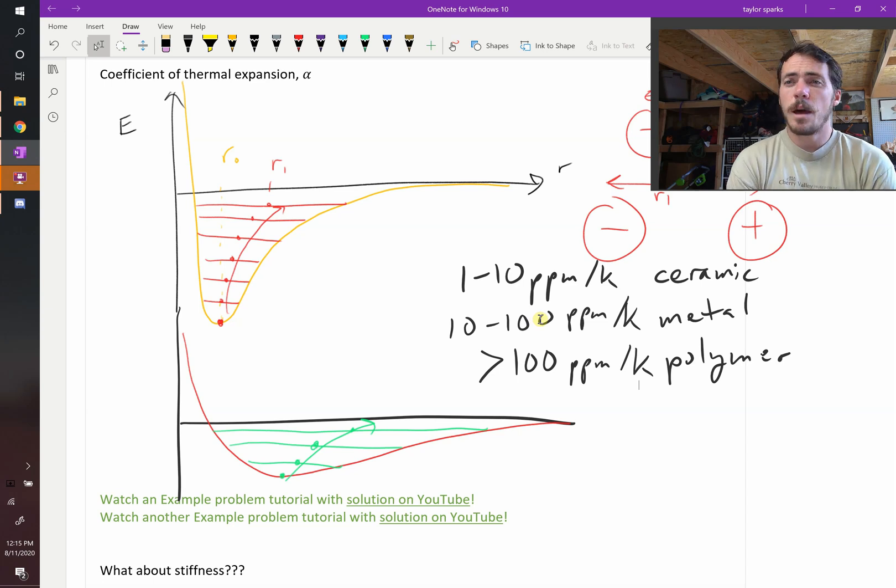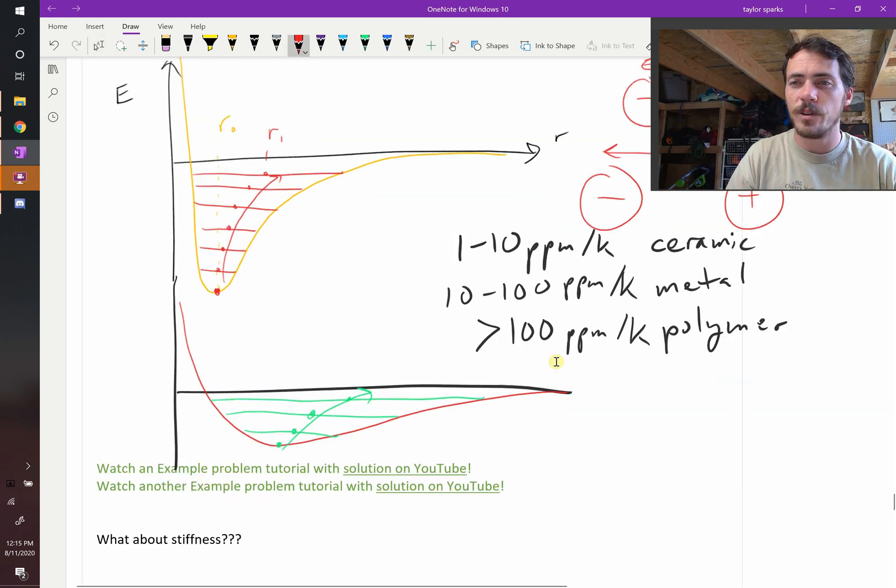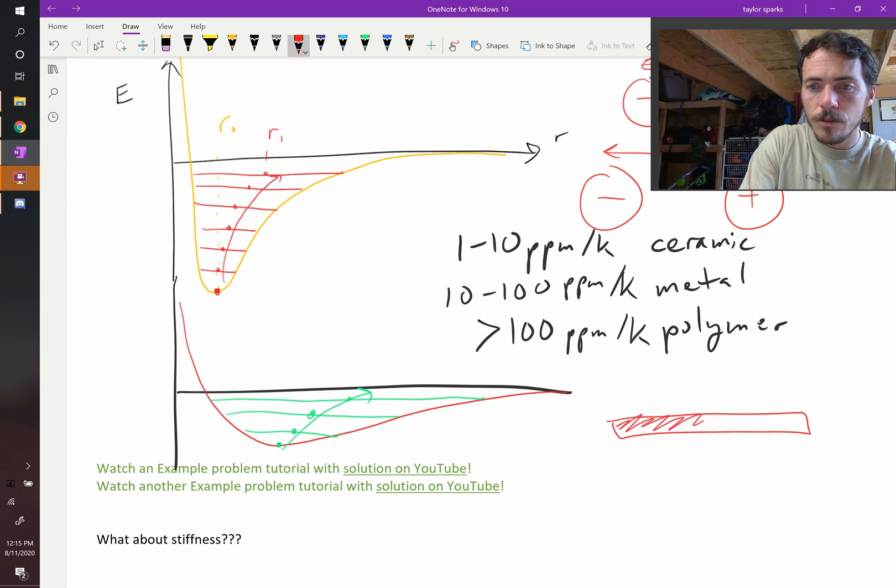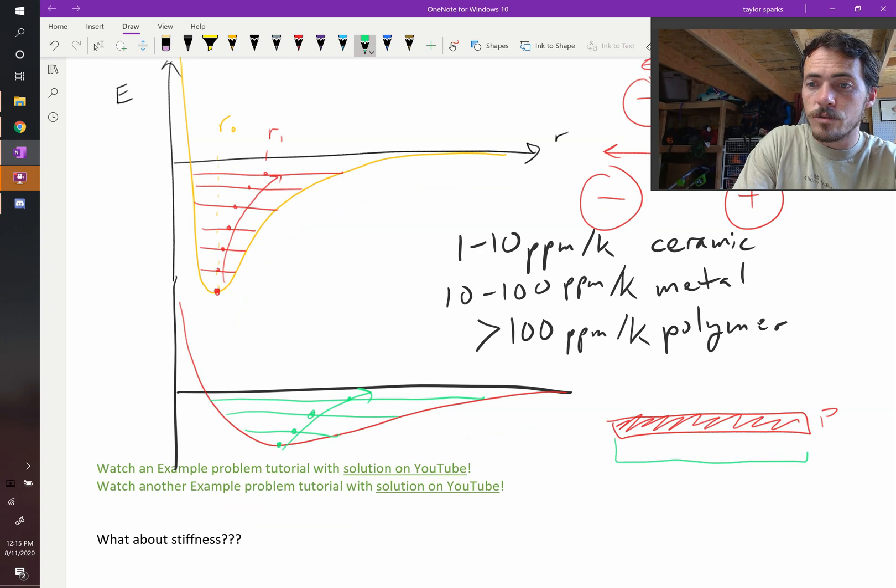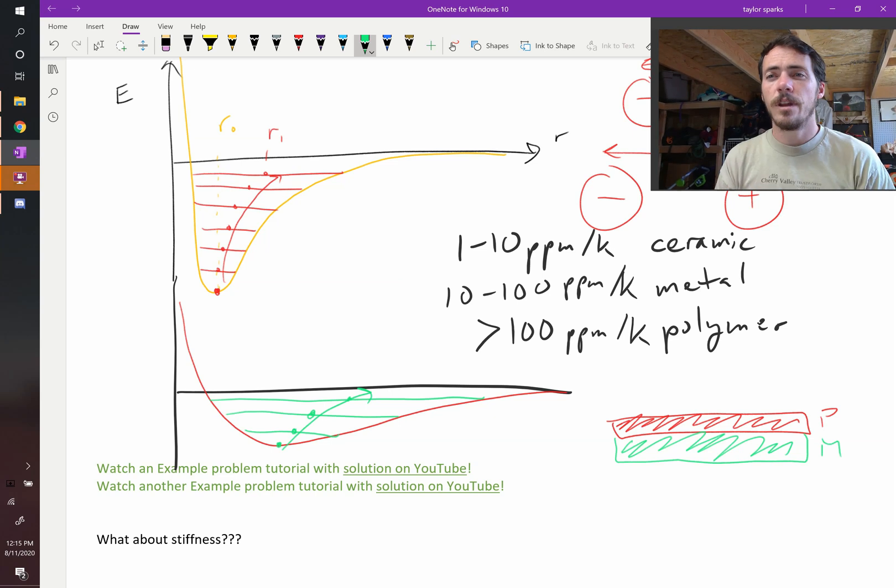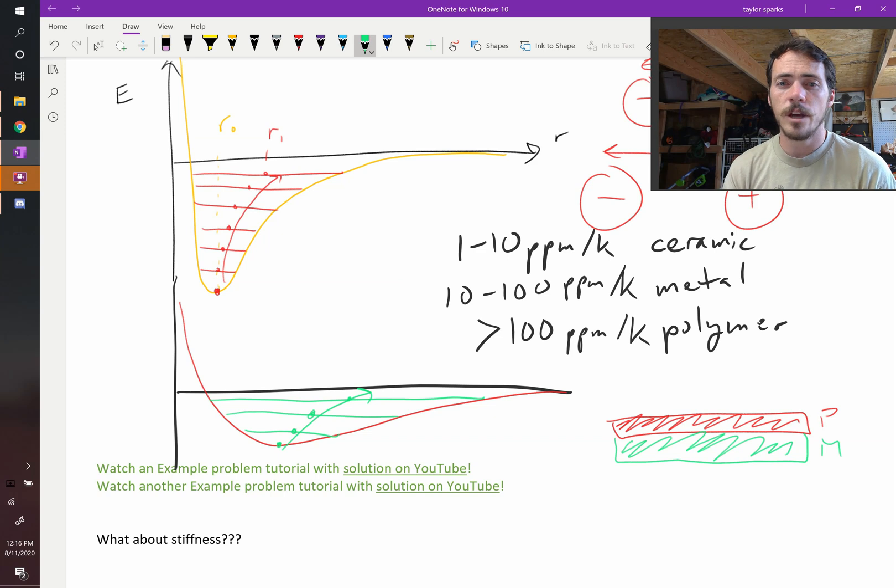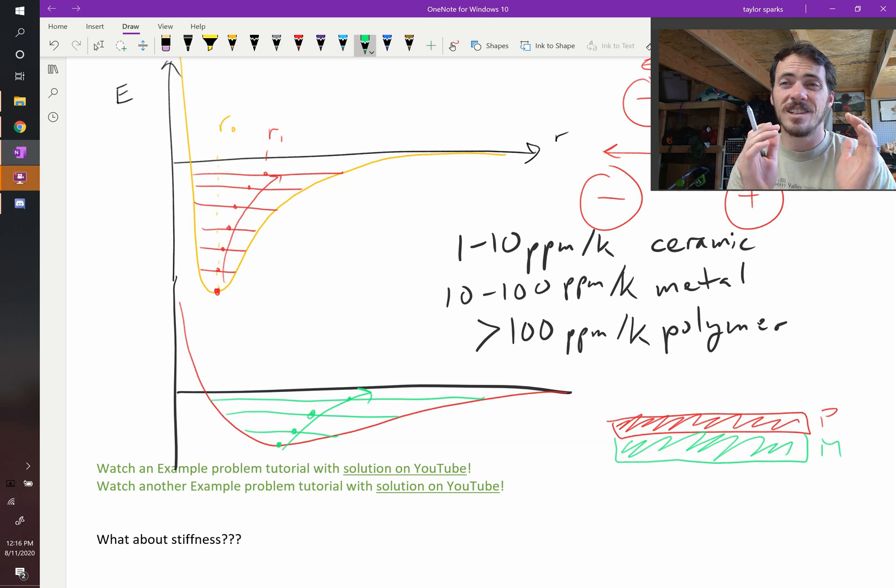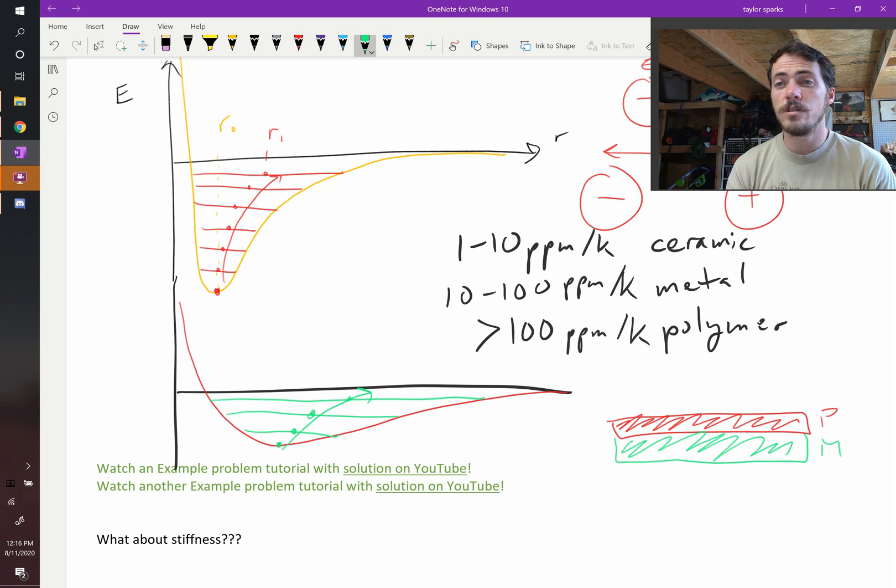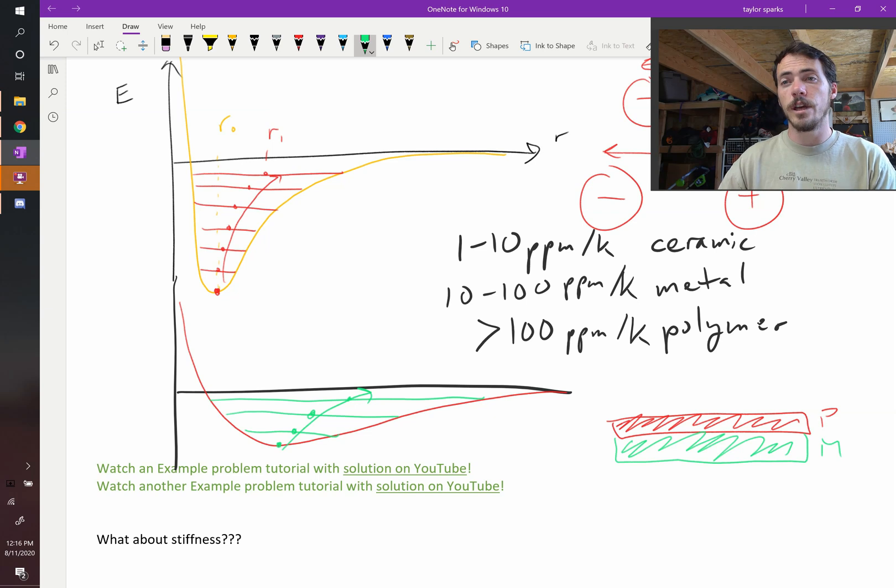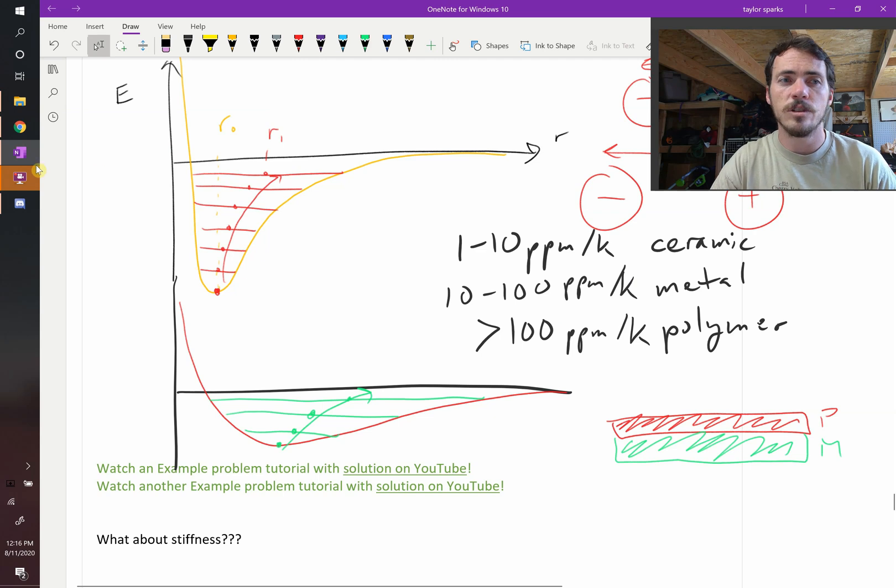What's going to happen when you make some sort of device, right? You make some handy dandy contraption for your next invention. And it's made up of a polymer right here, sweet, sweet polymer. And that is bonded with some sort of strong epoxy or something to a metal. What's going to happen to that material as you heat it up and then cool it down and heat it up and cool it down? Are they expanding at the same rate? No way. The polymer is wanting to expand more. The metal is wanting to expand less. So if the polymer wants to expand more and it can't, it's in a state of compression. The polymer is being, the metal wants to expand less, but it's being pulled a little bit. So it's under tension. This will cause de-bonding and de-lamination in lots and lots of materials. Actually thermal stress is something we're going to cover later on this semester. But that's the origin of them is that they don't all expand at different rates because they have different potential energy well curves.